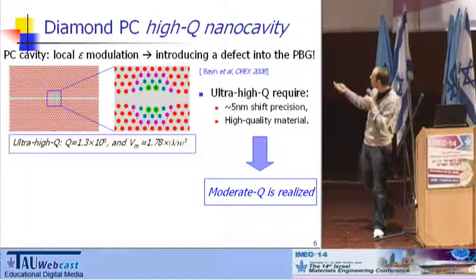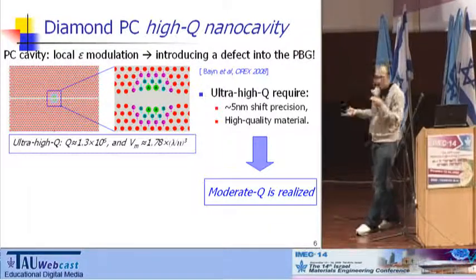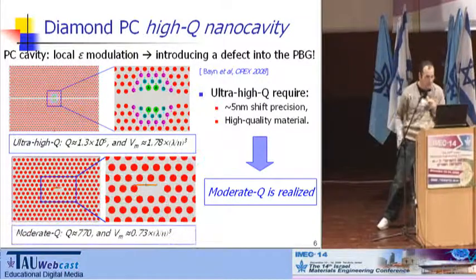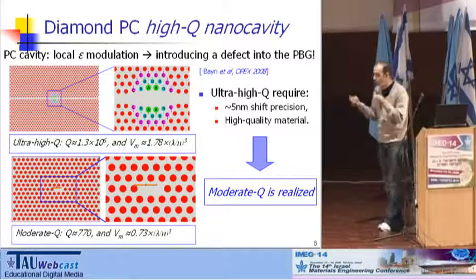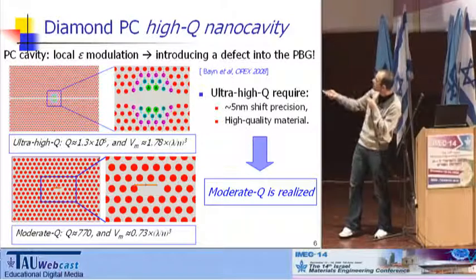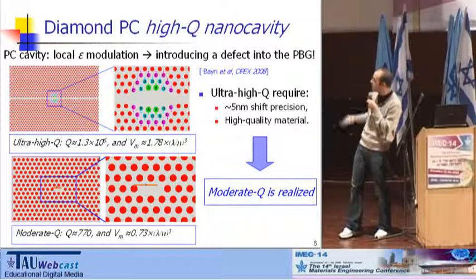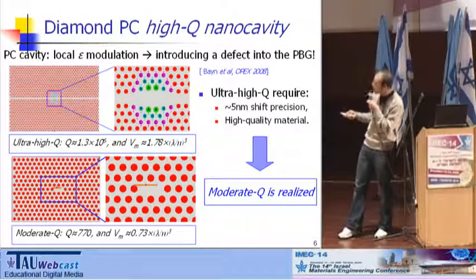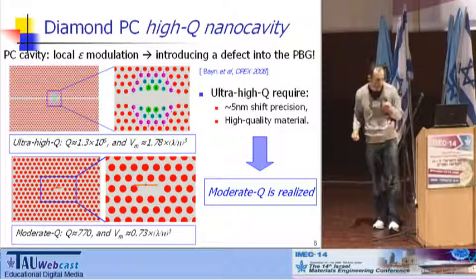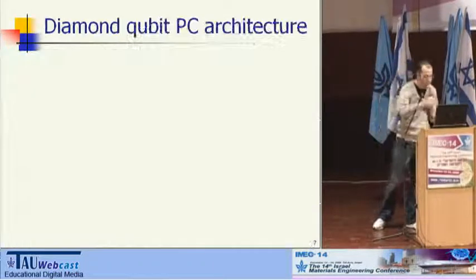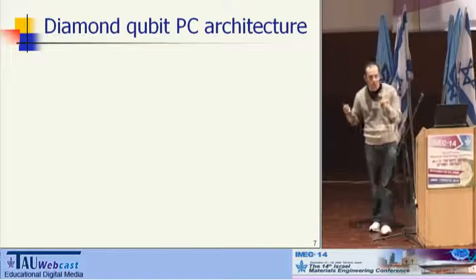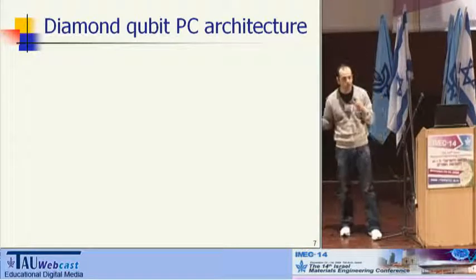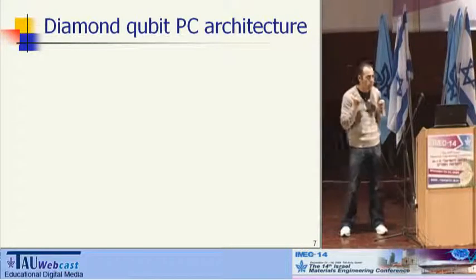So to start and to realize the first photonic crystal nanocavity, we decided to go to somewhat modest tasks, which are moderate quality factor cavities, and they are formed by the 3 missing hole technology. So we take this photonic crystal and just miss 3 holes in the middle. We obtain, or we should obtain, the quality factor of 800. Now, when the idea of the design of the photonic crystal is clear, I can turn to the fabrication.